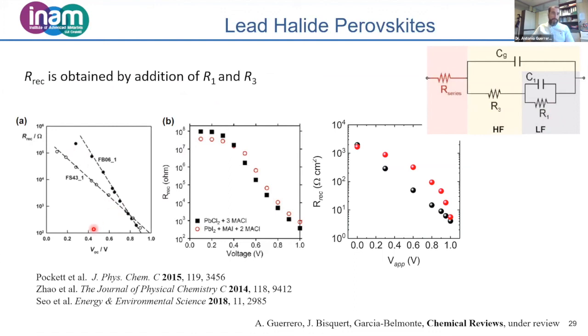We can plot the recombination resistance as a function of VOC, or applied DC voltage, we can change the experimental conditions, and then this helps us to compare different cells. For example, in terms of ideality factor, from this slope we can extract the ideality factor, or we can calculate the recombination current. So we get kinetic information from this curve.